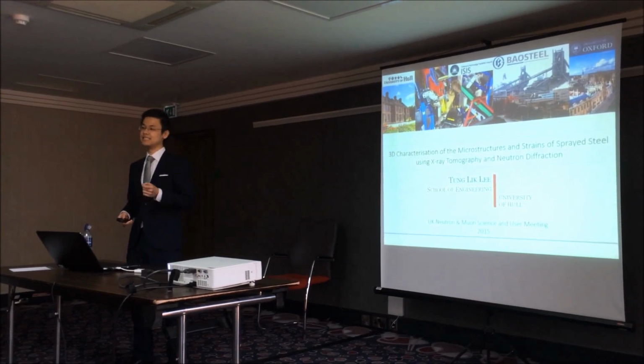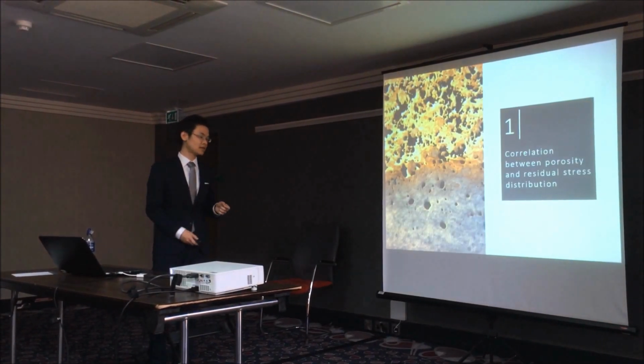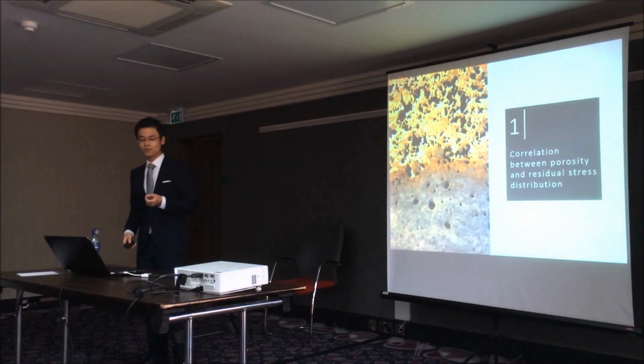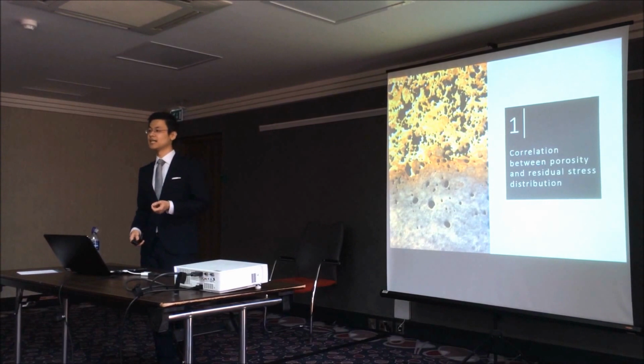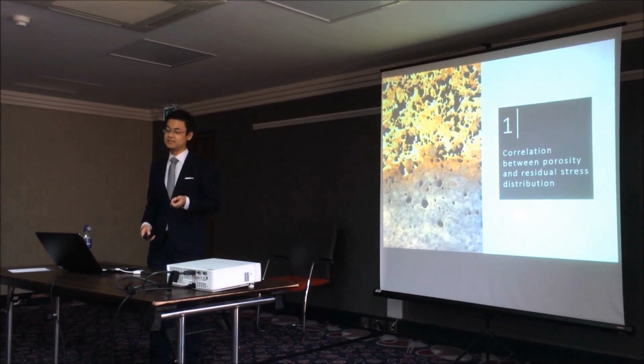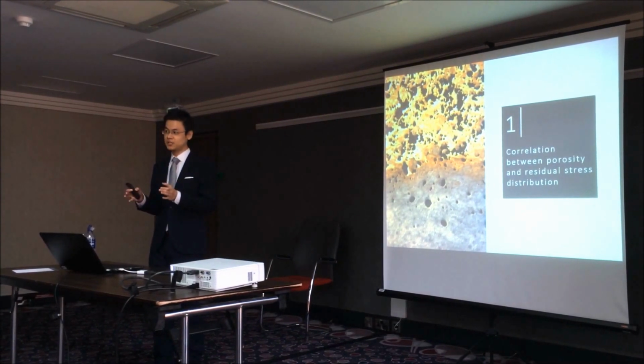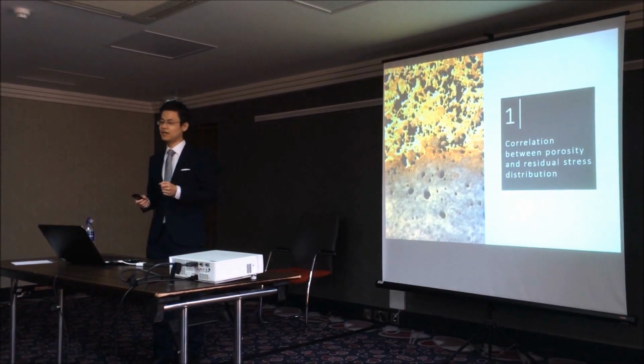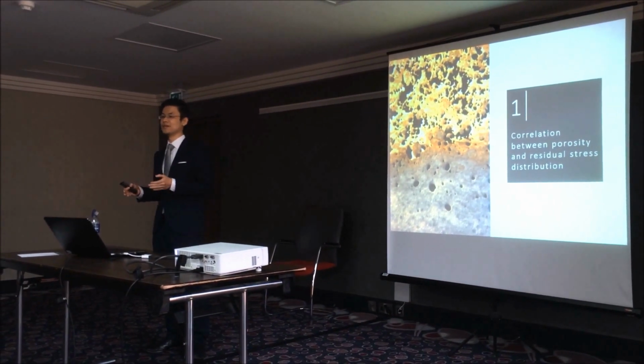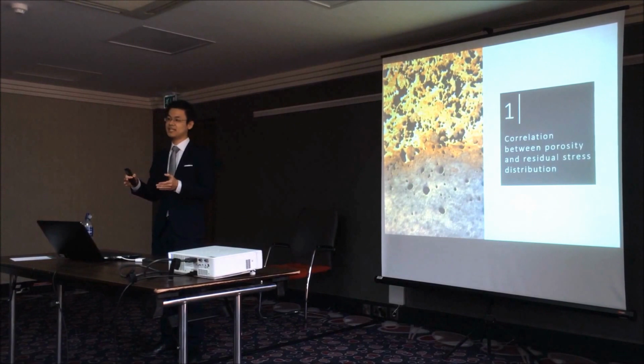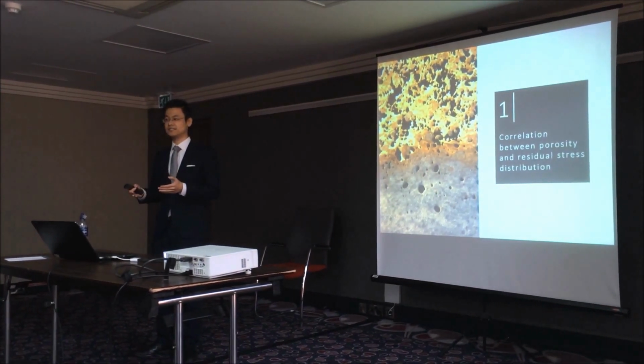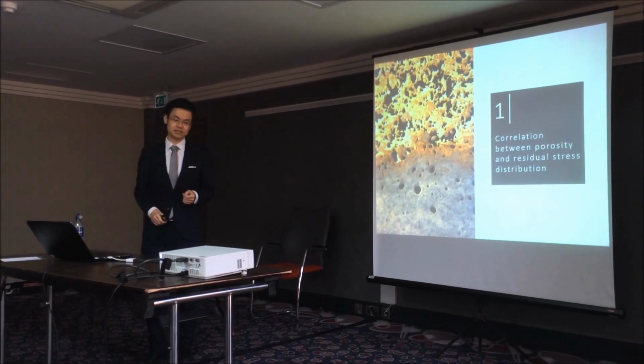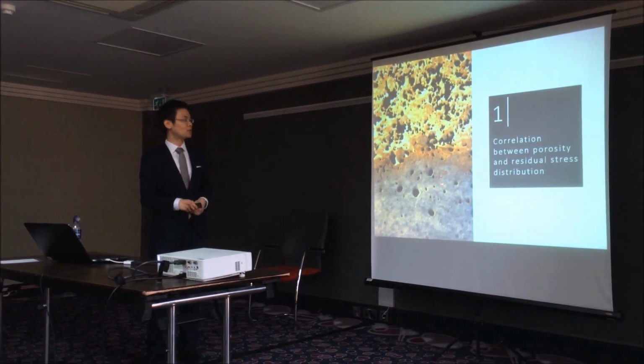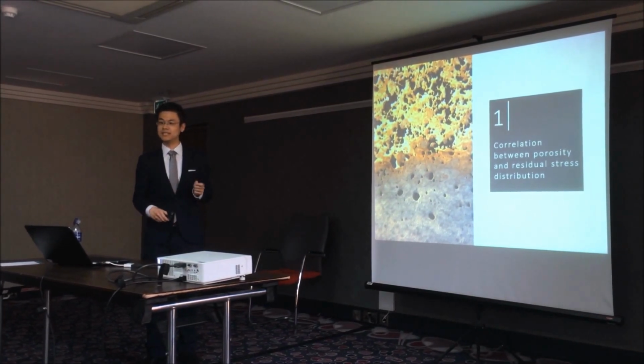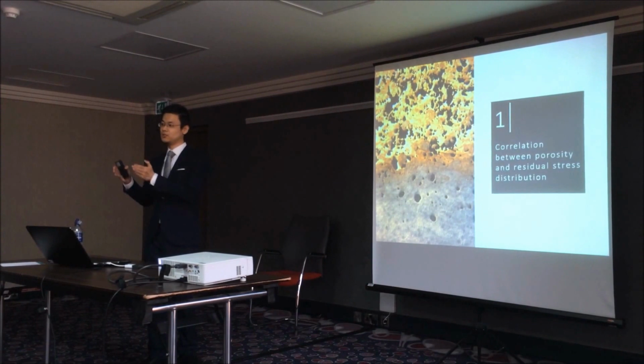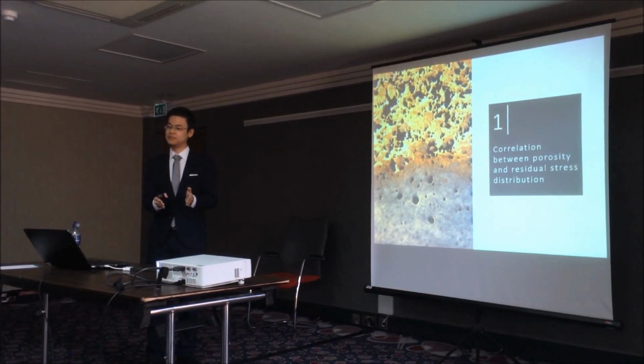Now, let me first highlight the key takeaway points from this talk. In general, when we measure residual stress, especially, a non-destructive method is ideal to measure the true nature of this residual stress in a component. However, it is due to this non-destructive nature as well that we may miss some of the hidden features in a component that could affect residual stress, such as porosity. Therefore, we manufactured a sprayed component with a step change in terms of porosity to allow us to study a correlation between porosity distribution and residual stress distribution.